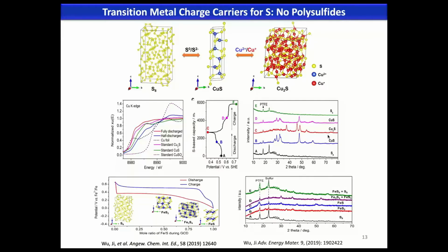And this is not just for copper. As far as I know, it's probably applicable widely to transition metal ions. For example, in this case for iron, we have the ferrous iron, and it's also very reversible. We have ferrous sulfide, and we don't have a polysulfide dissolution problem. Everything is solid. So this is something I hope to share: you can design your sulfur batteries, potentially considering the charge carriers of transition metals.